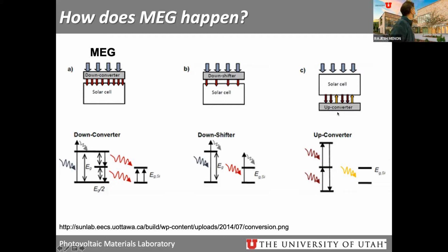The more common approach is what's shown here, which utilizes an up converter, also difficult to do. But in this case, the red photons pass straight through the solar cell, and there's an up conversion. Some of them, not all of them, some of them are absorbed, of course. The up conversion simply converts it to higher energy photons with less flux, the fewer number of photons. Again, energy band diagram is easier to understand. You come in with 2 red photons, you get these 2 absorption events, generating 1 yellow photon, so it has higher energy, which is then absorbed by the silicon. So anyway, this one's a little bit confusing because what's happening is that the red photons pass through, and you're simply reflecting with this upconverter with this yellow photon, which is then absorbed by the silicon. So you get this extra effect as well.